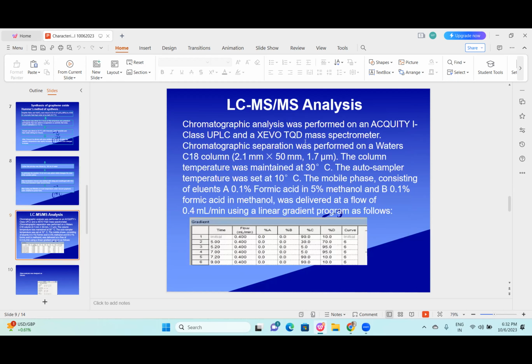LCMS analysis. Chromatographic analysis was performed on an Acquity I-Class UPLC and XEVO TQD mass spectrometer. Chromatographic separation was performed on the Waters C18 column, 2.1 mm by 50 mm, 1.7 micrometer diameter. The column temperature was maintained at 30 degrees centigrade. The autosampler temperature was set at 10 degrees centigrade. The mobile phase consisted of A, 0.1% formic acid in 5% methanol, and B, 0.1% formic acid in 100% methanol. And the flow rate was 0.4 ml per minute using a linear gradient. This is the mass analysis.